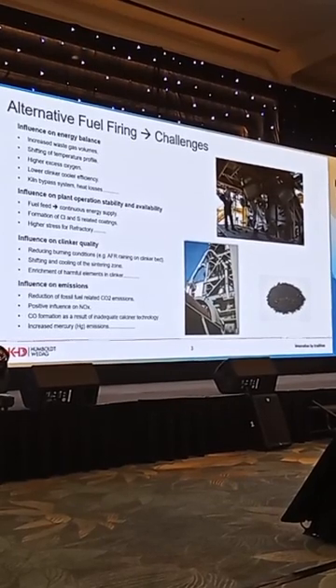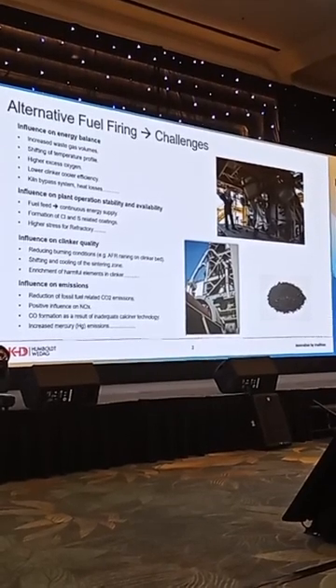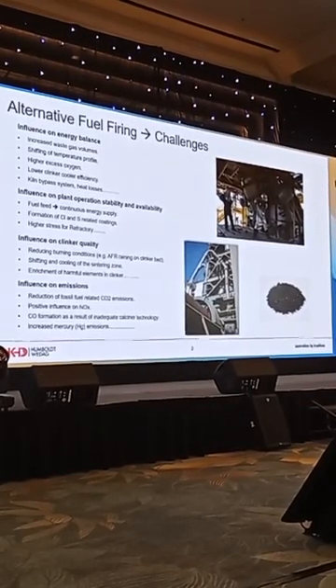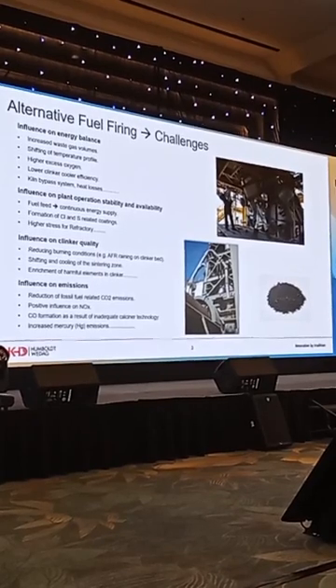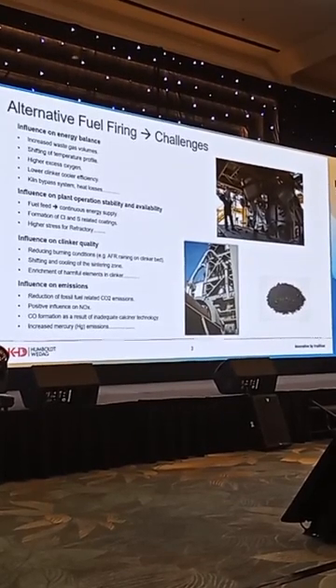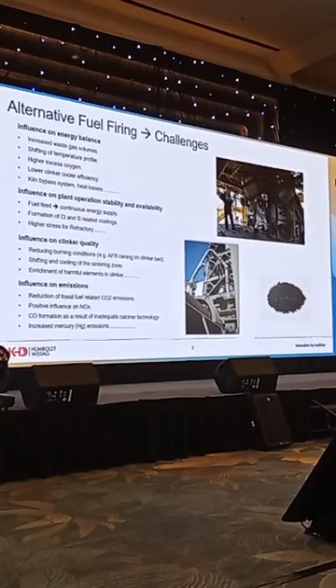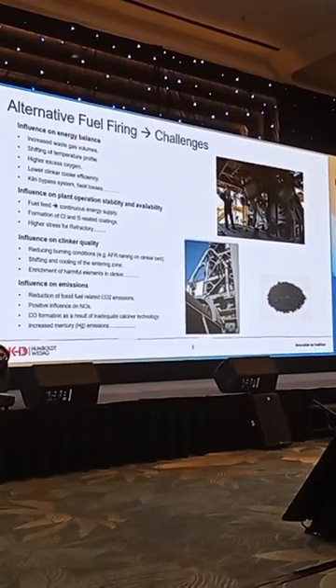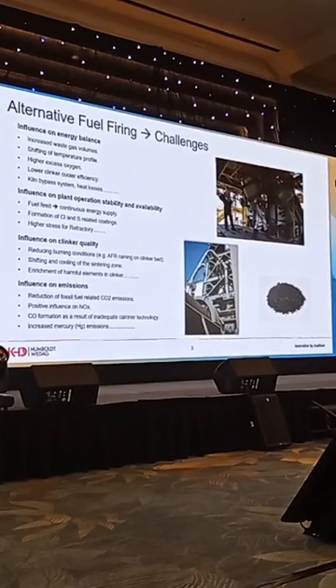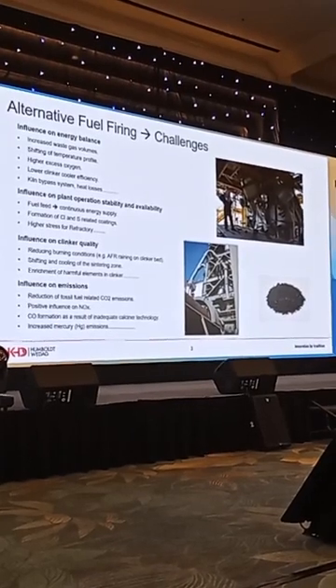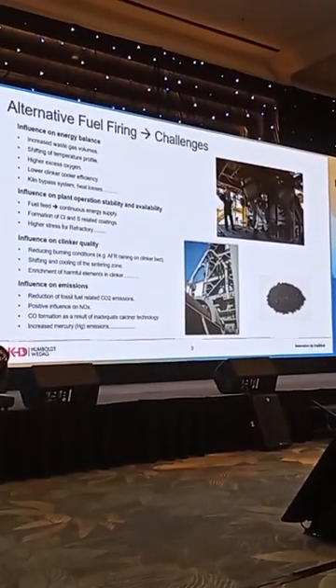And also by feeding these alternative fuels, you are putting inside a high amount of chlorine, sulfur, all these other things. This means the chlorine already coming from the raw material, which is maybe already creating problems in the calciner riser duct and the lower cyclone stages in the preheater, can also be influenced by these alternative fuels with an additional amount of chlorine and so on. So you are having problems then maybe in these areas, and you have to add also a kiln bypass system, which is creating an additional heat loss of some kilocalories.